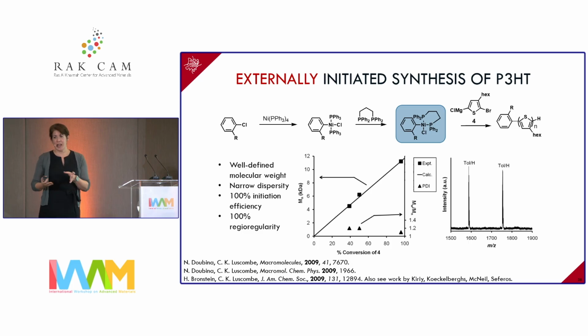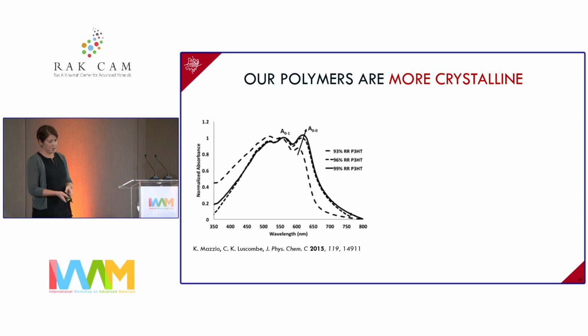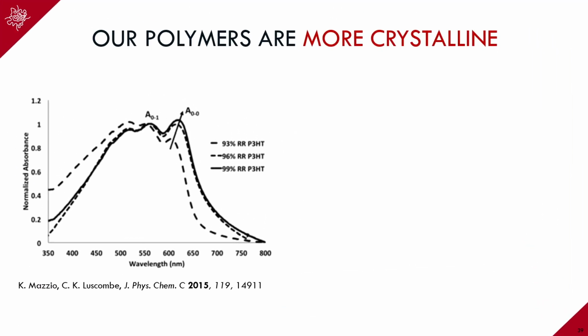Oftentimes I get asked, well, who cares? Who cares if the synthesis is great? Maybe if the material functions, who cares about the defects and so on? So I just want to show you some quick slides to show that actually having a well-defined material does indeed help with improving the properties of at least electronic materials. This is a UV-vis trace of a typical polymer, and enhancement in the shoulder peak right here tells us that we have greater crystallinity.